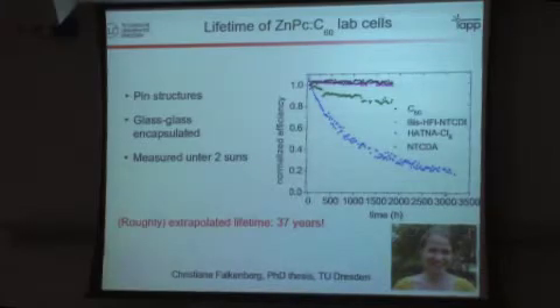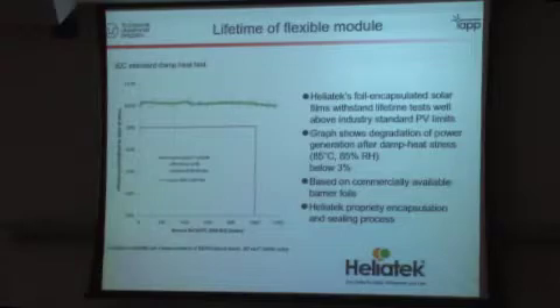Now this is not really practically relevant because we won't use glass as substrates, but it tells that the intrinsic stability of these organic materials is excellent. One comment is that you first of all need to encapsulate very well. The second point is you need to block UV. If you don't block UV, these lifetimes go down, but in practice you need to block UV, which can be done technically. Also, I want to show a more practically relevant result, which is again taken from Heliatek.